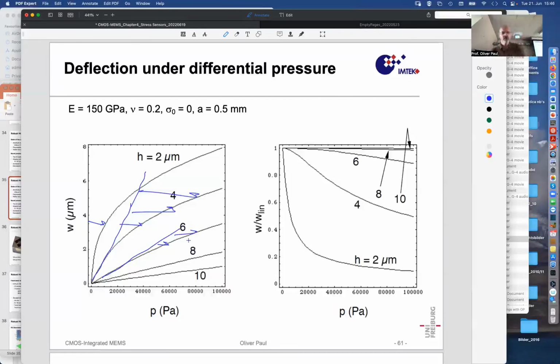And you see that for thick membranes, first of all, the deflection is much smaller. Of course, it's stiffer, cannot be deflected, and it's much more linear as a function of pressure. So if you would like to have a linear sensor, a mechanically linear sensor as a function of pressure up to 100,000 Pascal, 1 bar, then 10 is certainly better than 4 or 2, where you have mechanical nonlinearities.